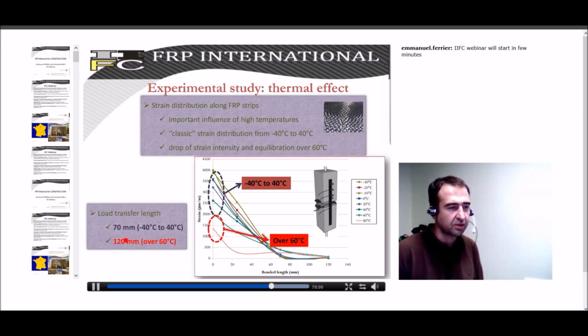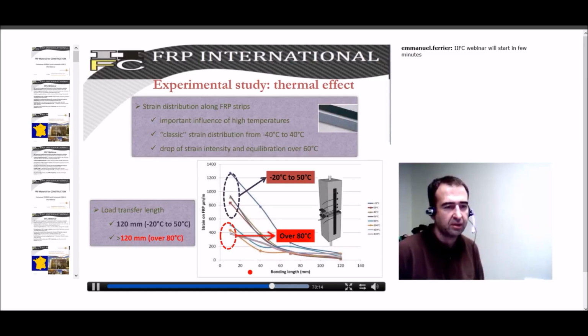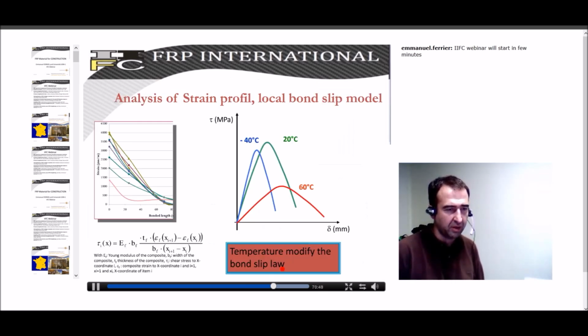So the load transfer length changes and depends on the temperature, which is quite new because all the equations basically have been developed for a constant value of transfer length. For the other system, the same observation can be made, with different values. You can see that very low temperature increases the strain very locally. That may explain that we maybe get some initial internal strain that may create some debonding before the loading. And then the behavior becomes very smooth when we increase the temperature. We are below the glass transition temperature, but very near this value. So temperature modifies the local bond slip model. That is our main conclusion and main issue about this, because the local bond slip model essentially depends on the strain profile you have.